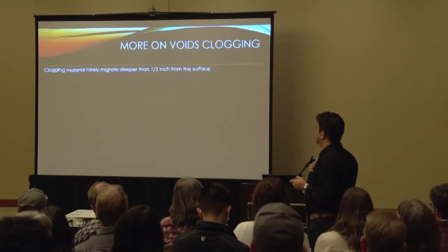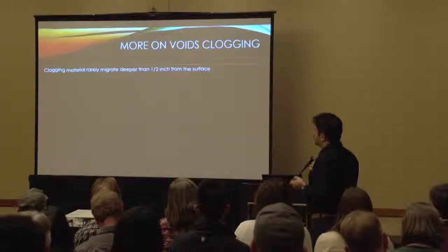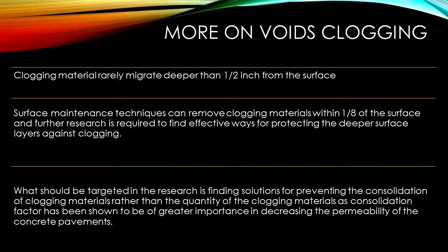So let's get some more information about voids clogging. Number one, clogging material rarely migrates deeper than half an inch, okay? So if you can manage them on the surface, they will not go deeper, based on the studies. Most of them will be captured on the surface within half an inch of depth. Number two, unfortunately, cleaning, like sweeping and vacuuming, can only clean 1/8 of an inch, okay? And with the existing knowledge, we need further research to solve that issue. And number three is that the clogged materials, in the course of time, will consolidate and get more firm, and they are harder to control.